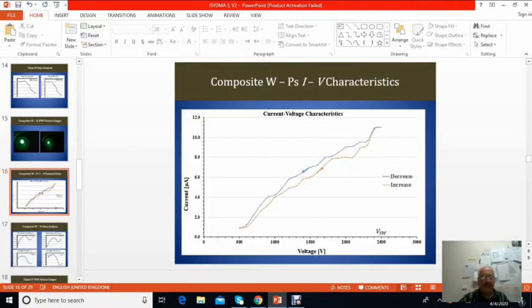Now, this is the tungsten polystyrene current-voltage characteristics. This is the increase cycle. Of course, this is the increase and the decrease cycle after the switch-on phenomenon occurred. So, with the metal, which is tungsten, we can see the coating produced a switch-on phenomenon, which we will not see with the carbon fibers. This is a normal procedure with carbon fibers, so it was the same with other coating materials.